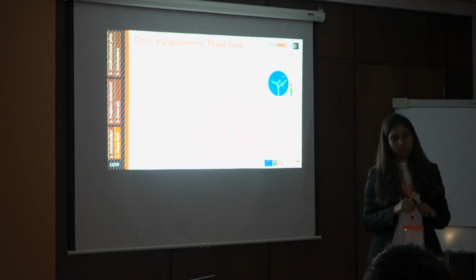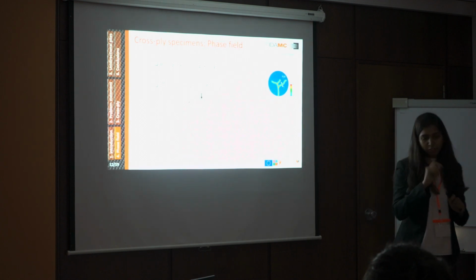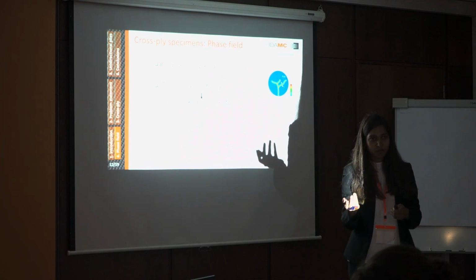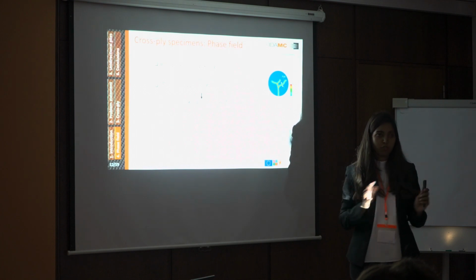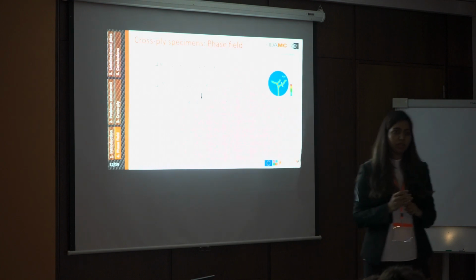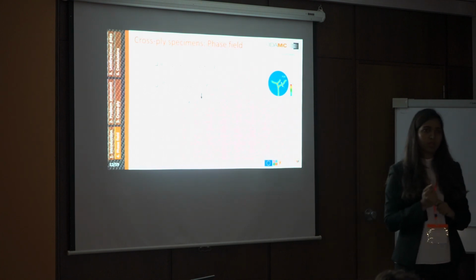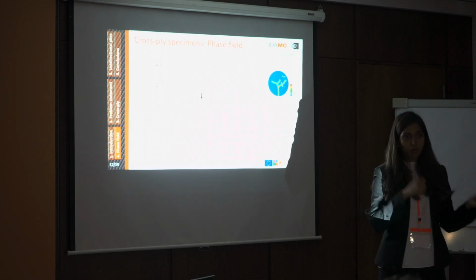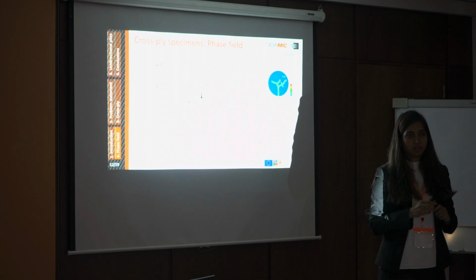Okay, thank you. For the AT2 model, there is a problem because the first increment itself is a non-zero value. That's why we are not considering AT2 in our models. But we still checked the results with all the formulations. For AT2, maybe you should wait until it becomes 1. But 1 is a complete failure, which we cannot take into account for our intralaminar failure. Okay.